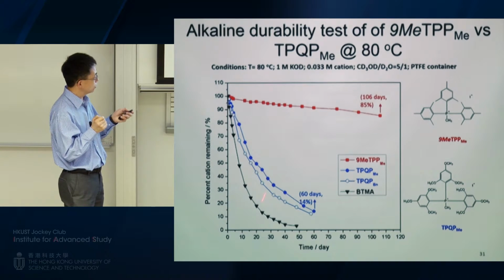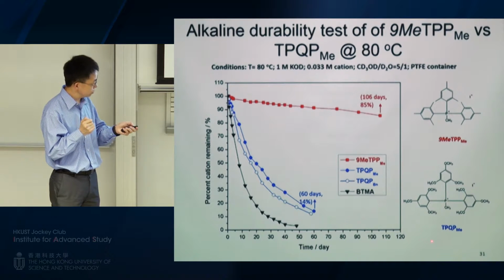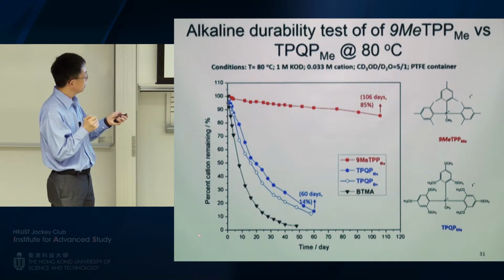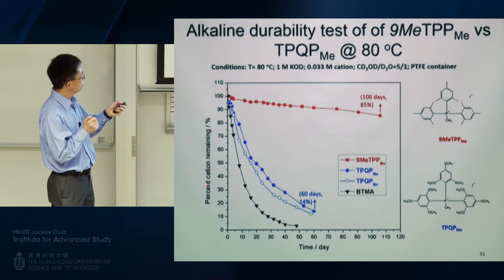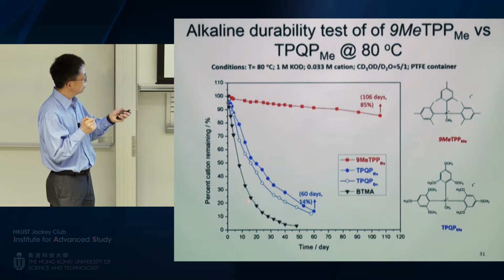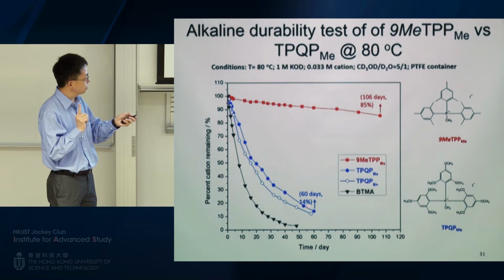So here are our results. The horizontal axis is how many days, and this is the percentage of cation remaining. This is the quaternary ammonium, and this is the quaternary phosphonium with 9-methoxy groups. But we made a change in terms of the fourth group. We used methyl instead of the benzyl group. I showed it to you before. The reason is we couldn't make the benzyl group go in here. The steric hindrance is too big.